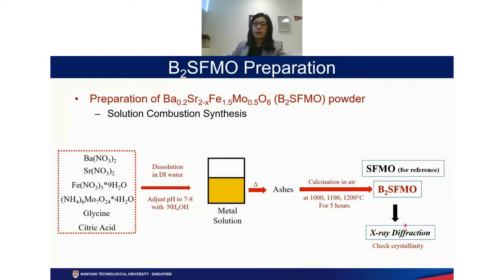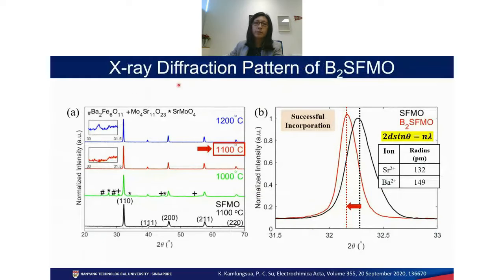So we first check the XRD to see whether we get the right crystallinity under these different calcination temperatures. Here is the X-ray diffraction pattern for BSFMO. We calcined at these 3 temperatures, with a reference to the SFMO calcined at 1100 degrees C. And you can see that for BSFMO calcined at 1000 degrees C and 1200 degrees C, there is some impurity phase that's visible, while for the calcination at 1100 degrees C, the XRD looks very clear. So there is no impurity phase spotted, and also the pattern is almost the same as the SFMO.